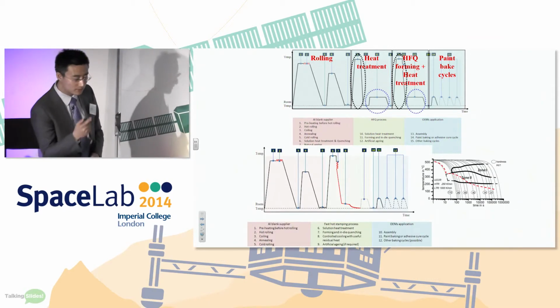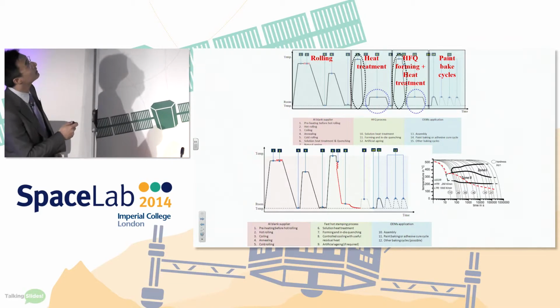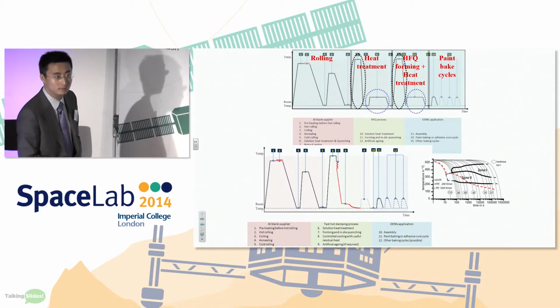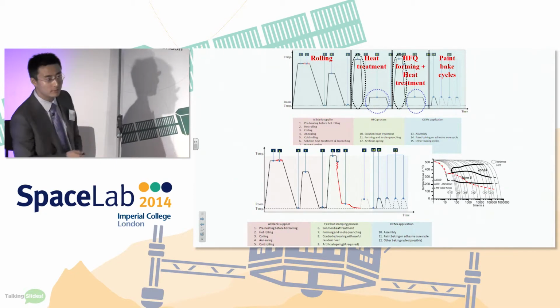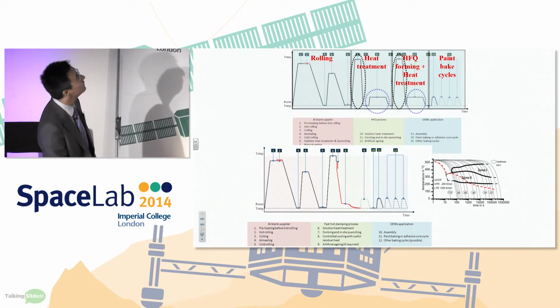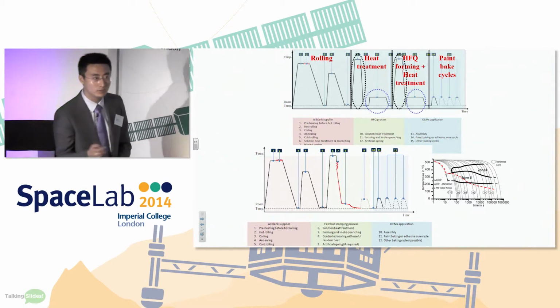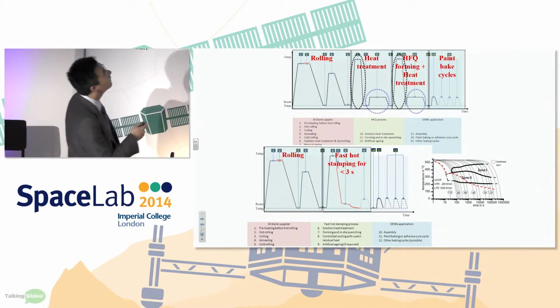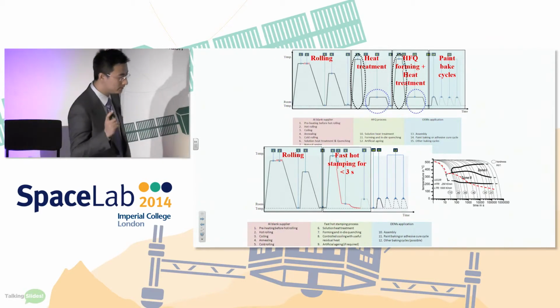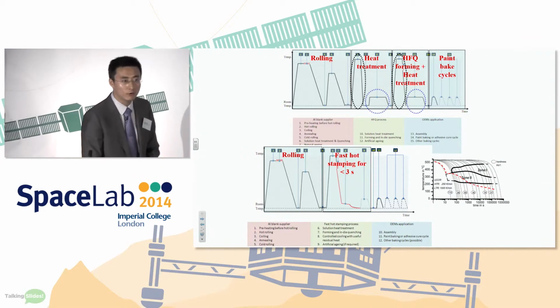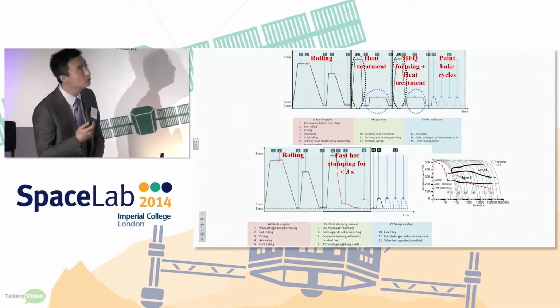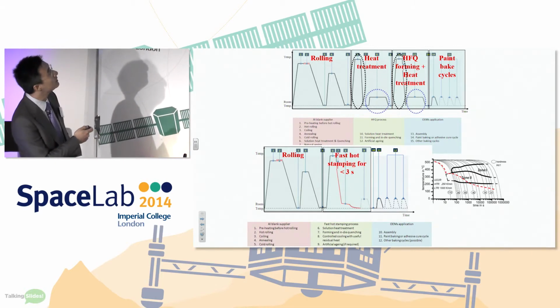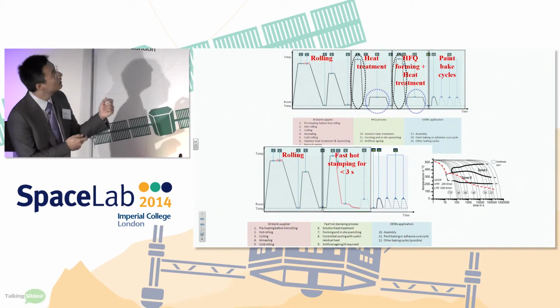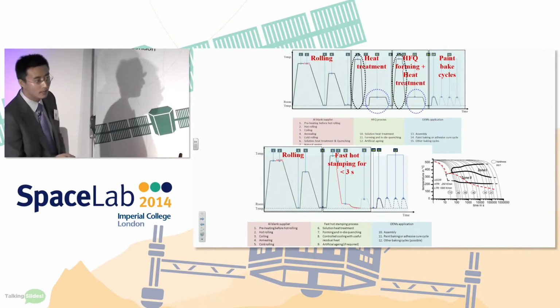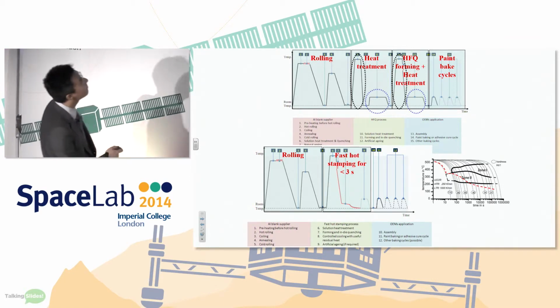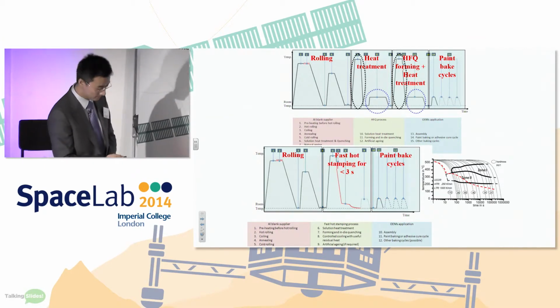And recently we have convinced the material supplier to provide us the material in the as-rolled condition. So they don't have to put heat treatment into their material production line. So we just use the material in the as-rolled state for HFQ forming. And also here, we use some dedicated equipment to determine the key forming parameters of this new forming process. We determined the critical cooling rate, critical cooling temperature, and the critical soaking time. These are the three key forming parameters in this technology.